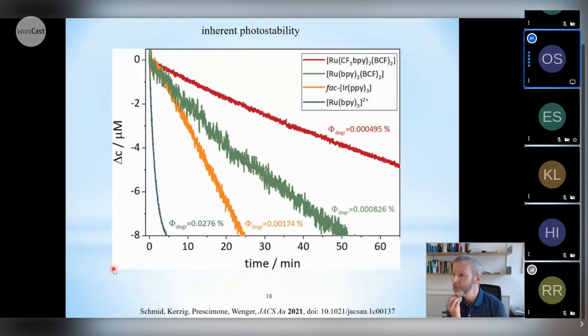But the one thing that surprised me most was when Lucius Schmid and Christoph Kerzig performed these inherent photostability studies. What they did was something rather brutal. They took a cuvette containing micromolar concentrations of these photosensitizers and also of Rubpy, and they hit that solution with a 1 watt blue laser, steady state, full power. They saw very rapid photodegradation of ruthenium tris-bipyridine. After 5 minutes, it was all gone. But in the case of the cyanoborylated variants, here is Lucius's champion complex, this survives for very long irradiation times, even under these very harsh conditions, which usually you would likely not have in a photocatalysis experiment. So again, a very enjoyable project for me to work with these young talented chemists.